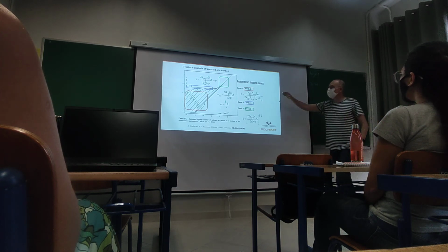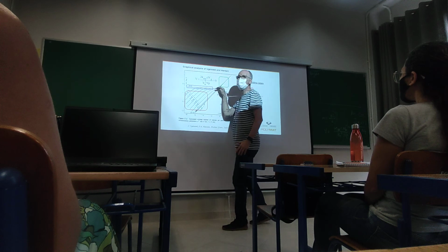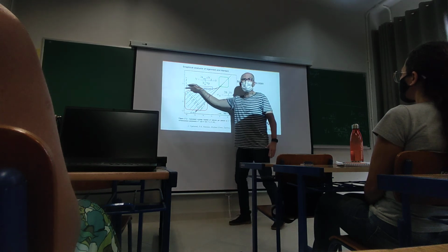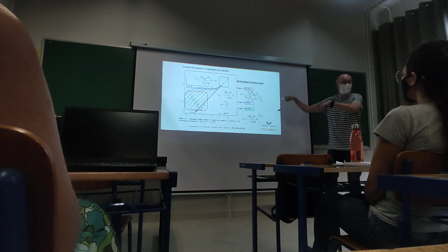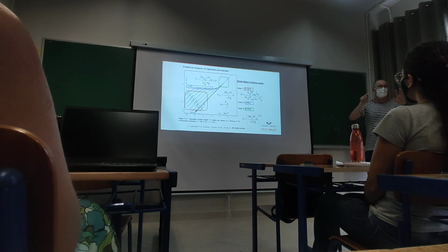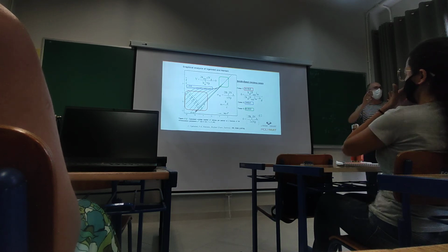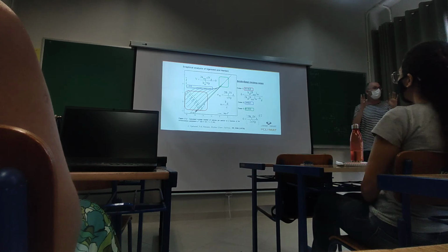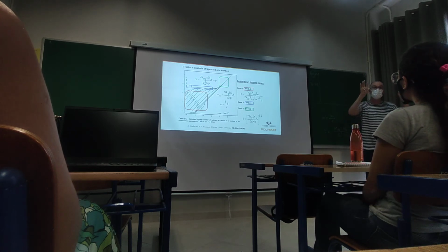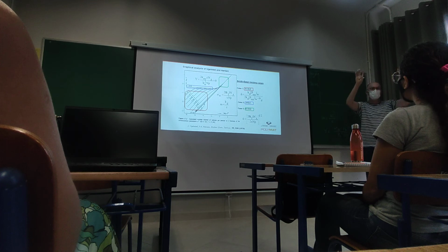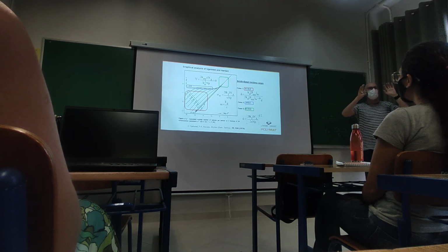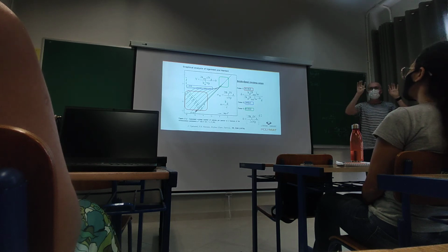So this is a very special case, but this is the ideal case for emulsion polymerization, because this is where you will have the good control of what I was saying yesterday that was unique in emulsion polymerization. The case in which molar masses and polymerization rate can be increased simultaneously. Because this is where the system will be fully compartmentalized. Okay? We have particles with 0, particles with 1.